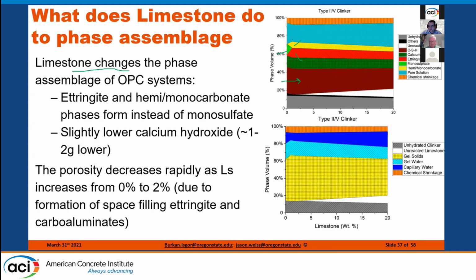So this point here corresponds to the point of minimum porosity, minimum amount of solution in the system, and that's really due to the phases that are forming in the overall system. As we move away from 2 to 3% limestone, all of the phases that form, as we move to the right-hand side, are the same phases. We're left over with a little bit of unreacted limestone, or unreacted calcite, in the overall system. So the whole thing that we're showing here is we have slightly lower calcium hydroxide when we've got limestone in the system. We've got ettringite and monocarbonate phases forming, and we saw the porosity decrease as we added a little bit of limestone, primarily due to the monosulfate conversion.